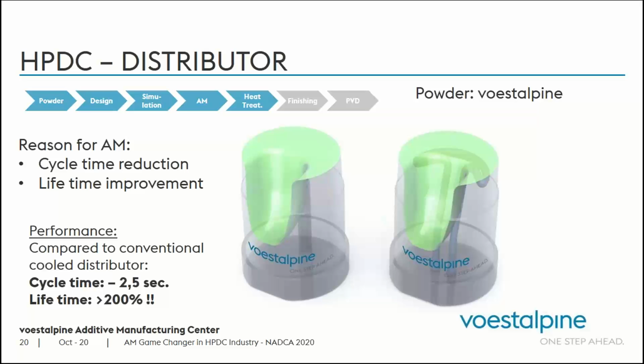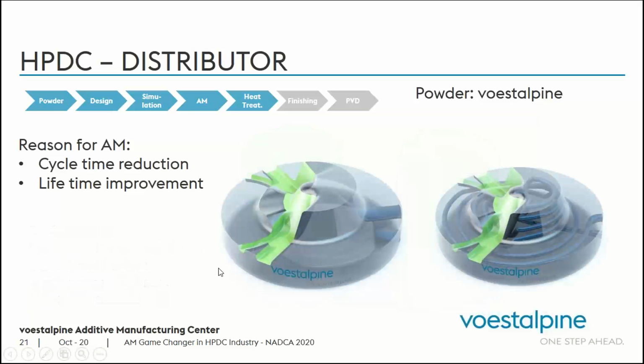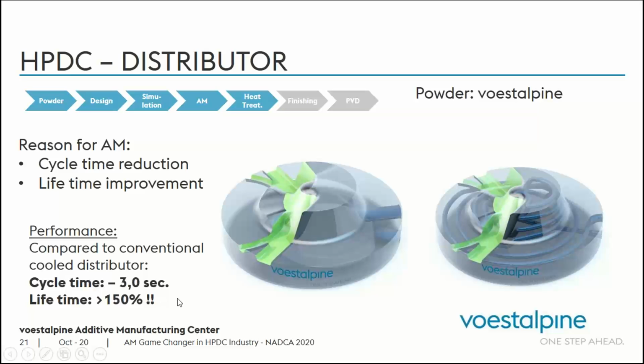So this is just one of the success stories that we had in high pressure die casting. Another distributor as well, the diameter was around 250 millimeter or a little bit less. The reason for using AM was a cycle time reduction and lifetime improvements. We were able to lower the cycle time by 3 seconds. This is compared to a conventional cooled distributor.